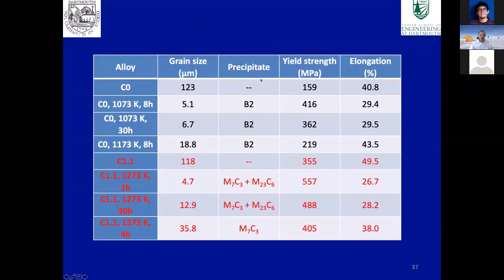So if you look, this is the undoped alloy, and this is the doped alloy. We've got these different grain size materials. So in this one, we've got B2 particles forming after the thermomechanical treatment. And in the carbon doped alloy, we've got these different carbides forming.